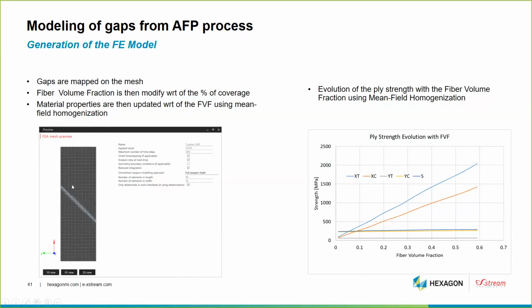If you have, for example, an element fully outside the gap, then we won't modify the fiber volume fraction. If you have some element which is just at the limit between the gap and where there is no gap, then we will adapt the fiber volume fraction based on its location with respect to the position of the gap. All the elements which are exactly in the middle of the gap will have a very low fiber volume fraction, so they will have the resin property in this case. This adaptation of the material property is done using mean field homogenization. Again, based on the position of the element with respect to the gap, we modify the material property, since one element can be exactly in the middle of the gap, and another can be at the limit between the gap and the ply.